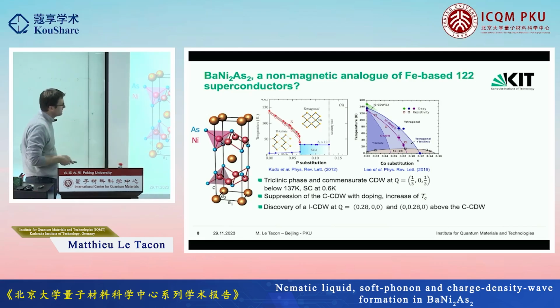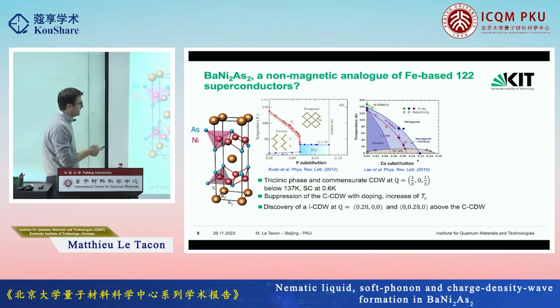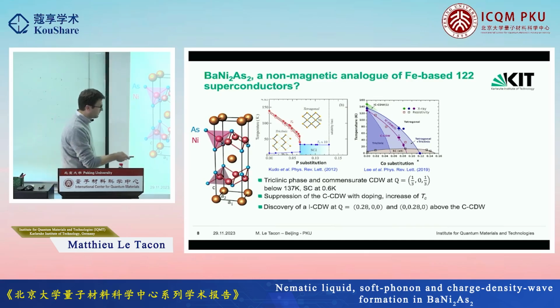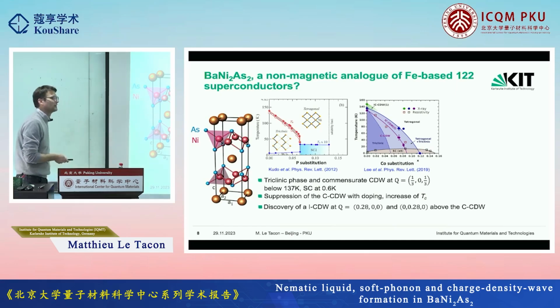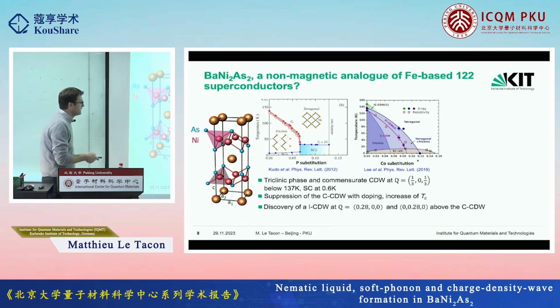But it was also realized later on that it is accompanied by a commensurate charge density wave, which has this wave vector, 1/3, 0, 1/3, but it also has 8 twins because of the triclinic distortion. So it's really a mess, the reciprocal space of that compound. Maybe I'll show it later.